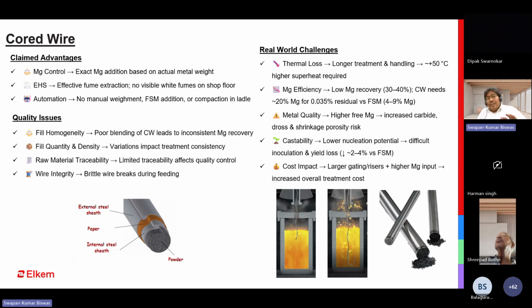In most of the cases, very rarely do they calculate this, but when they start facing these metallurgical challenges, then they start activities to find where it is going wrong. And in this case also, the treatment temperature is on the higher side. And magnesium recovery, as I already mentioned, is on the lower side, around 30 to 40%, as compared to the sandwich process, where you can achieve up to 80%.